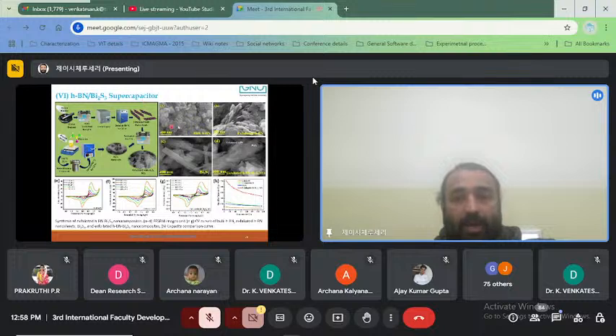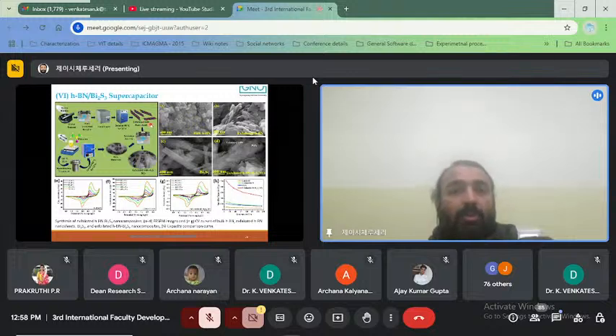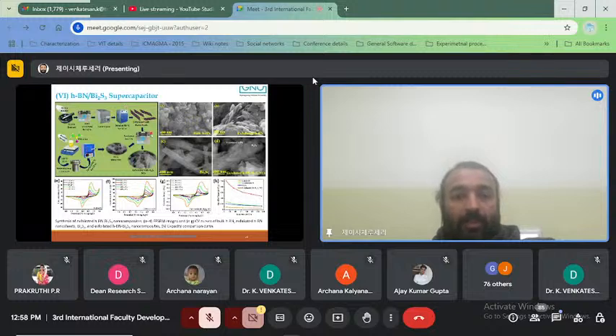So the hexagonal boron nitride. Also, synthesis is very easy. You can take the boron nitride, then do the bath sonication, centrifugation, dry it, and then exfoliate it. So it is that simple. But you may need to do it multiple times because sometimes the HBN nanosheets may not get exfoliated. So these are some of the synthesis methods which are shown, and also you can see that they are very good for supercapacitor applications. More than 750 coulomb per gram is the specific capacity achieved by this material, which shows its potential in next generation supercapacitors.